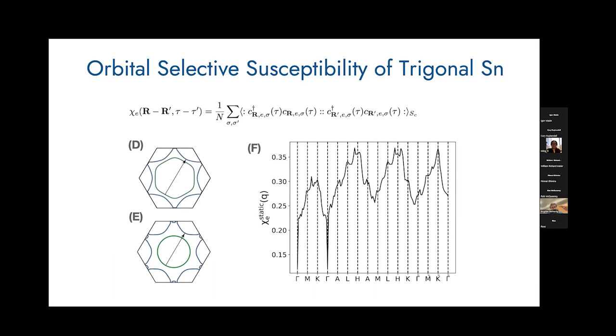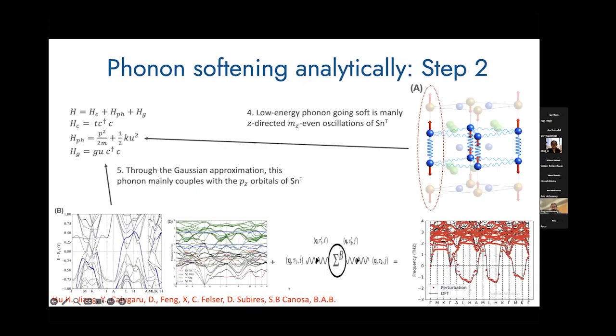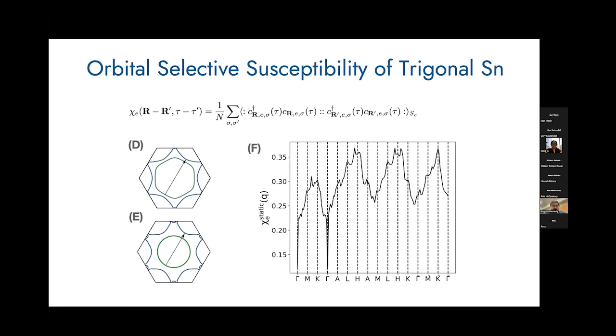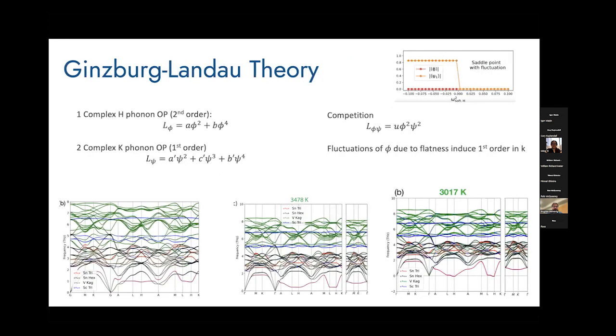Okay, you see it's a little soft here, a soft minimum at H. That's just a triangular dispersion. If I was looking in this plane here, this would be just a triangular dispersion of the phonon, which is given by the nearest neighbor of the susceptibility of trigonal tin. Okay, so now we can explain, obviously helped by DFT, there's no way we could have done it without DFT, but we can explain in some semi-analytic way the reason for the softening of the phonon at second order at the H point.